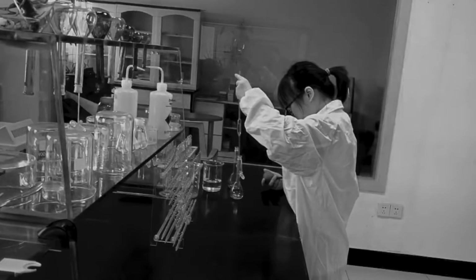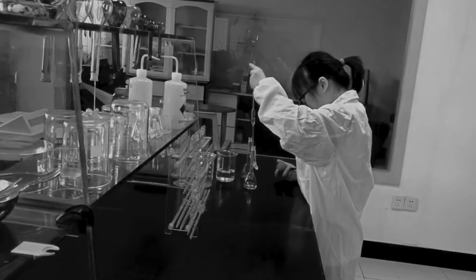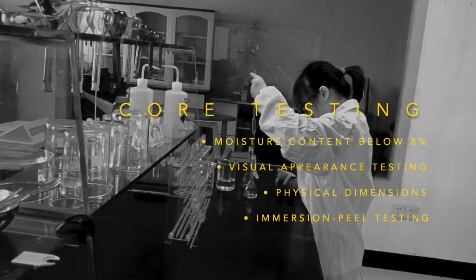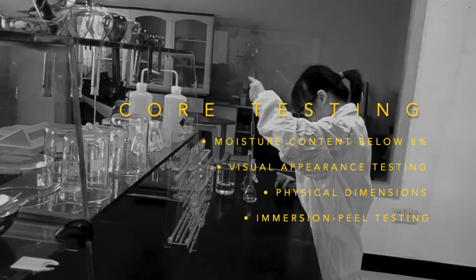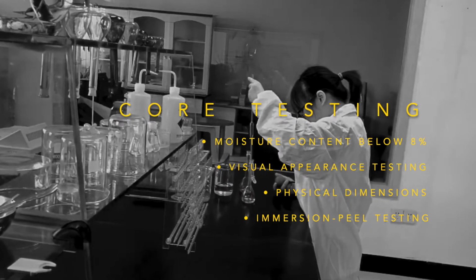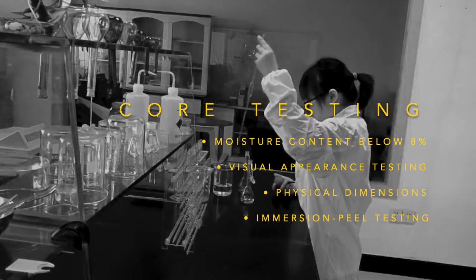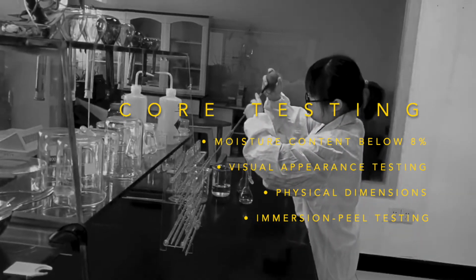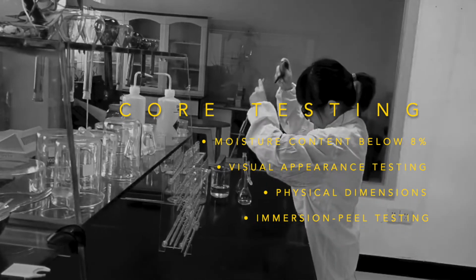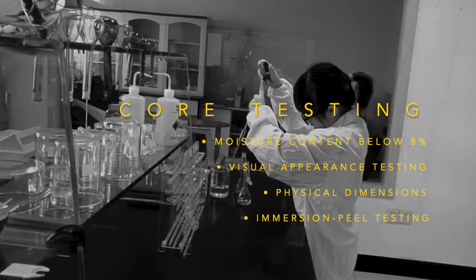Phase 2, raw material testing. Moisture content must be below 8%, this to prevent cracking, delamination, and stability issues after installation. During this phase, we also test all physical properties before and after an immersed peel test. This test is to ensure the strength and the bond of the adhesive used during the process.